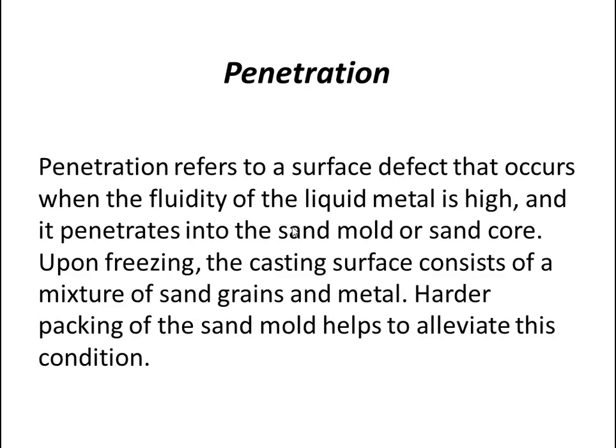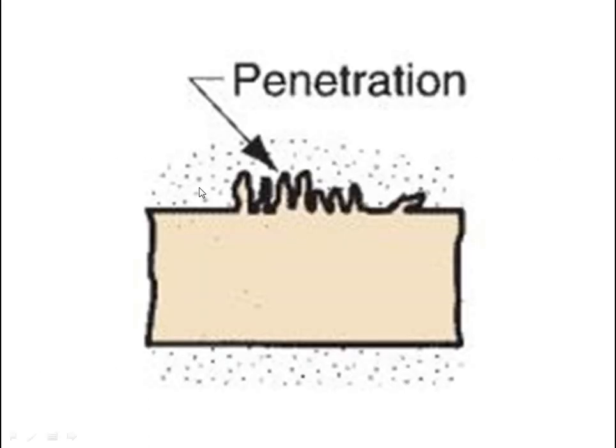Penetration refers to a surface defect that occurs when the fluidity of the liquid metal is high and it penetrates into the sand mold or sand core. Upon freezing, the casting surface consists of a mixture of sand grains and metal. Harder packing of the sand mold helps to alleviate this condition. There is a figure of penetration.